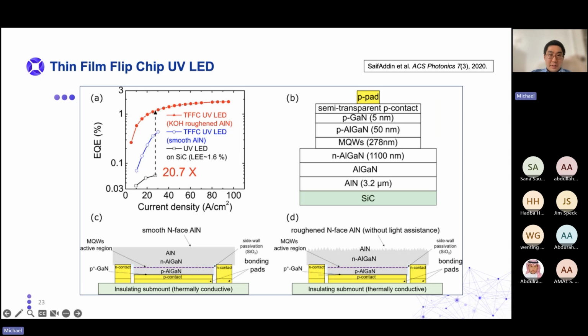So this is a comparison between the efficiency of the UVLED just on the silicon carbide versus the thin film flip chip UVLED device. So you can see that getting rid of the substrate and roughening the backside of aluminum nitride increases the light extracted from the device by a factor of 20, which is incredible. I wish I had this kind of light extraction on my current devices, but we will continue to work on that.